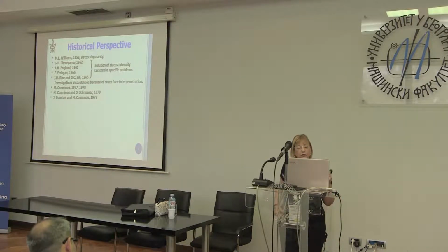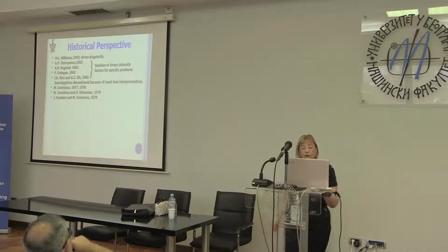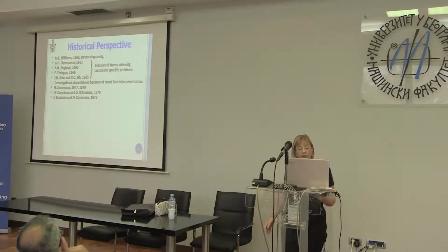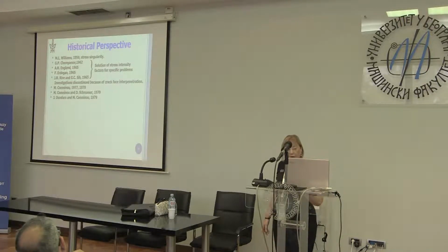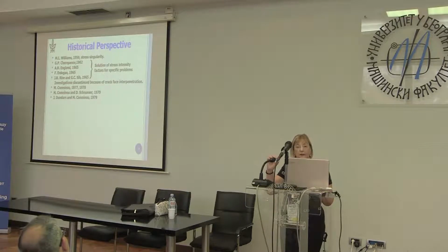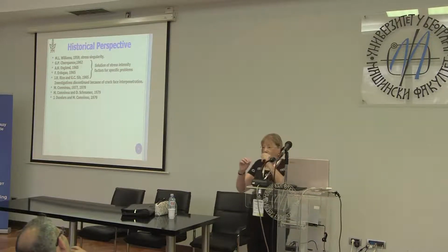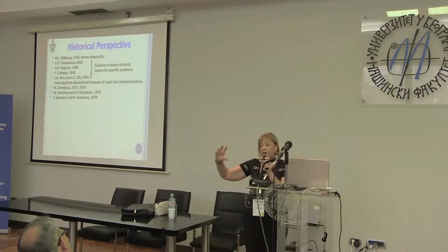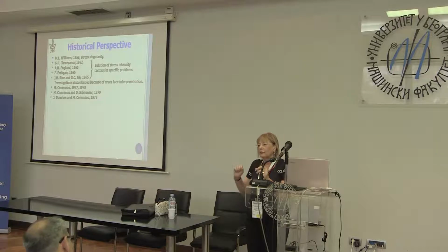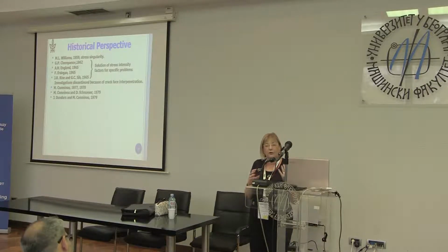Maria Comninou from the University of Michigan wrote a series of papers, one with her student Schmueser, I think it's Schmueser, and the other with her thesis advisor, Dundurs, where she assumes, I don't have a picture here, that there's a contact zone. In other words, there's an interface, there's a contact zone, and then the crack opens up. And what she's looking for is the size of the contact zone. So in the first paper, where it was tensile loading, she finds that the size of the contact zone is between 10 to the minus 4 and 10 to the minus 10 of the crack length, or the half crack length. She does a Griffith crack. She has a central crack in an infinite body along an interface.